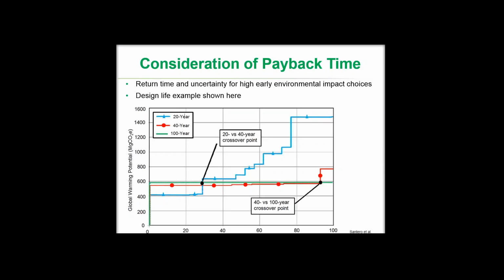So in this case, the 20-year design had a lower initial impact, but the analysis showed more frequent maintenance and rehab resulted in, over the longer life cycle, a much higher environmental impact. The 40-year design had a reduced environmental impact shown in red here, and that paid back after a relatively short amount of time. The higher initial impact of the 100-year pavement didn't really get paid back until way out in the future, which decreased the chance that we were actually going to get a payback.